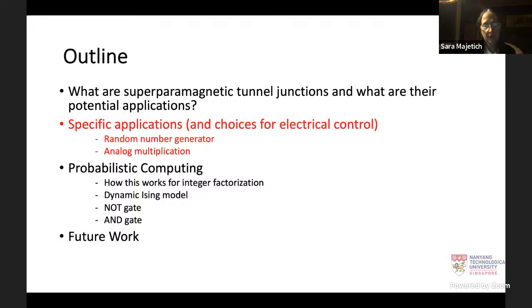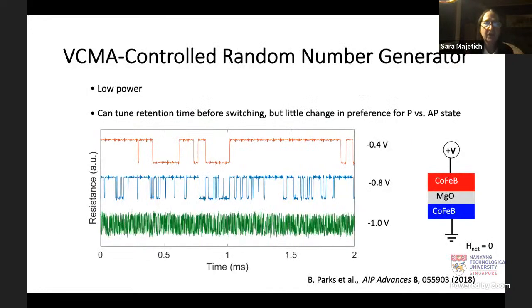And so we'll talk about two specific cases. First, the random number generator, where we use a perpendicular MTJ and voltage controlled magnetic anisotropy. Because it's voltage controlled, you're not sending much current across this, so you're not going to damage the tunnel barrier. With low power, you can get tunability.